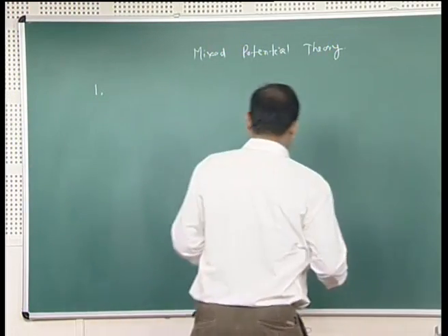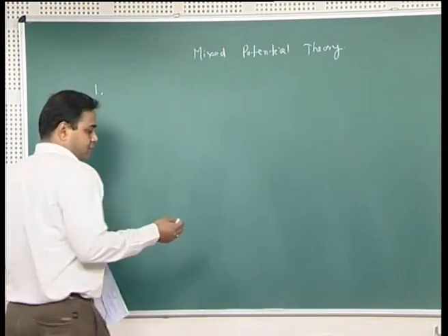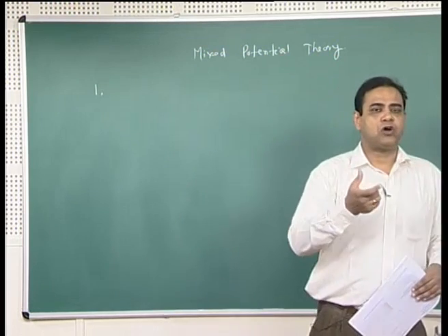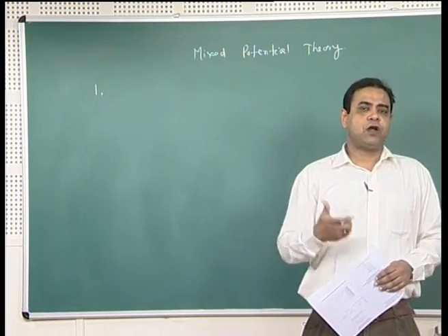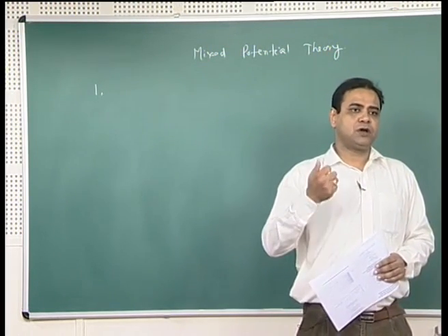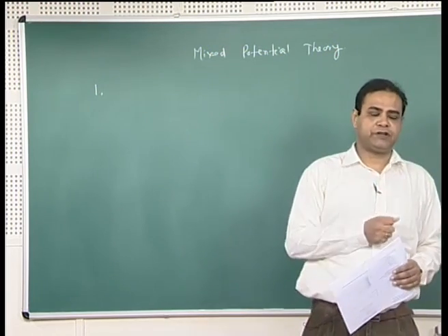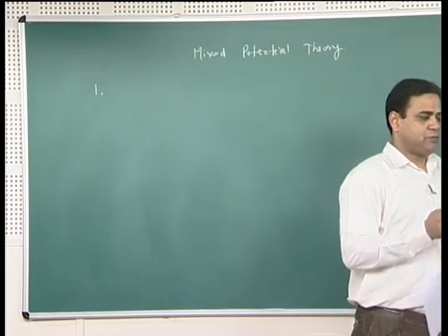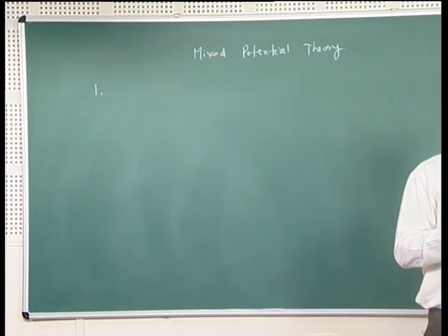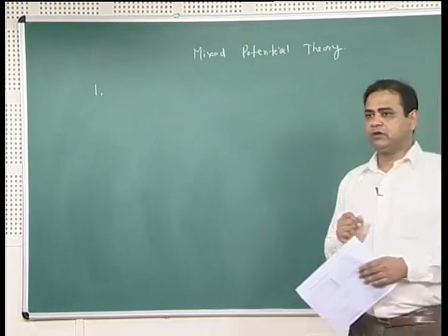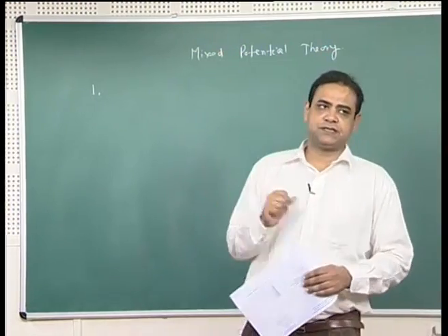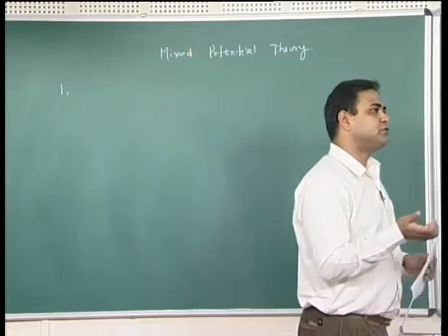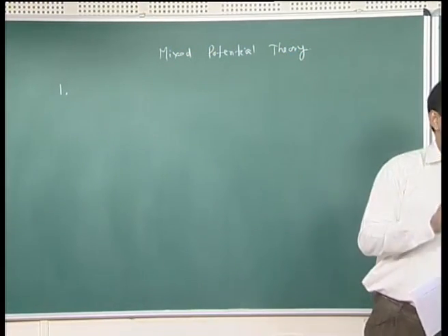One says that any corrosion reaction can be divided into two or more partial reactions, either oxidation or reduction reactions. We have given an example in the case of zinc. If you dip one zinc rod in deaerated HCl, then the main reaction is hydrogen evolution and zinc corrosion.